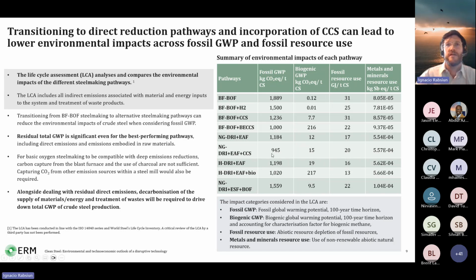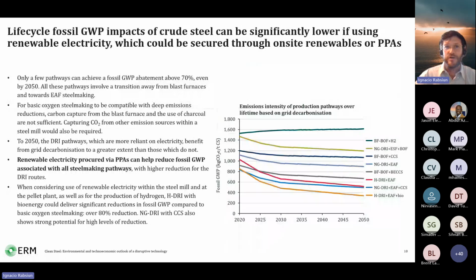What you can also see here is that, interestingly, for the direct reduction pathway, it's not just hydrogen-based direct reduction that is attractive from a GHG emissions perspective. Natural gas-based direct reduction, when retrofitted with a carbon capture plant, can lead to relatively low emissions. That is because emissions tend to be more concentrated in a single source, the natural gas reformer for the direct reduction plant, and they are not as diffuse as in the basic oxygen steelmaking process. However, there remain very significant residual emissions that may be more challenging to deal with, like the upstream methane emissions.